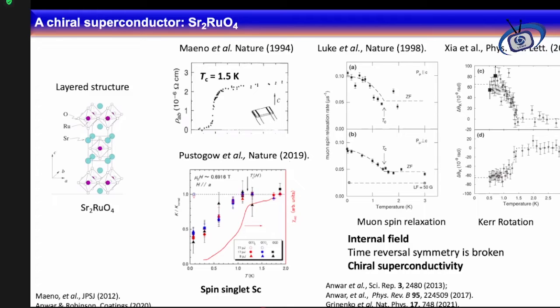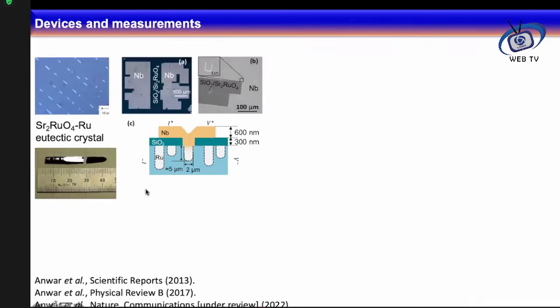And then by combining all these results and our recent research, it is established that this superconductor should be a chiral superconductor, meaning that its order parameter is continuously changing with the direction, and that breaks the time reverse symmetry. Then I selected this superconductor. We can grow very nice single crystals of this superconductor. Thin films are difficult, but the single crystals we can grow up to a very high quality.